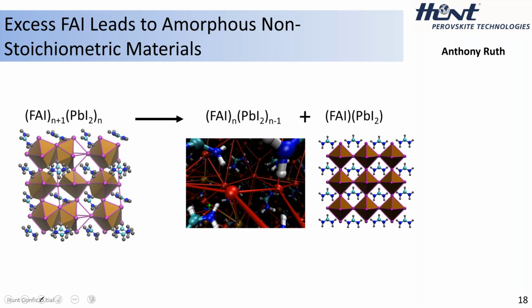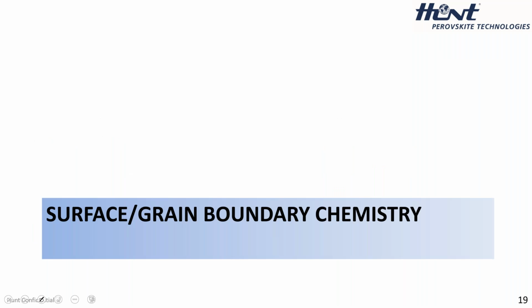But there is something that I believe is super stoichiometric FAPbI3 that exists outside of the crystallites. If you don't have this material, you don't have a good functioning material. Now the problem is that you have an exchange, right? You have this super stoichiometric material that lies on the surface or in the grain boundaries, and it can go from there into the crystallite, and the crystallite can move mass, translate mass from inside itself into the grain boundary. So you have this exchange. We've been doing some DFT calculations to represent this, but this is more a transition to the next stage here, where we want to focus in on those components, the surface and grain boundary chemistry.